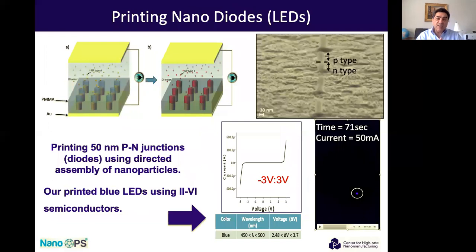So we use the same interconnect technology, but in this case, we did not use metal. We use a 2-6 semiconductor, in this case zinc selenide. You print the n-doped part first, then you print the p-doped part where the light comes out. You print them on a conductor, and then basically you connect them. You have a transparent conductor at the top, and you have a conductor on the bottom. And then it gives you the light.